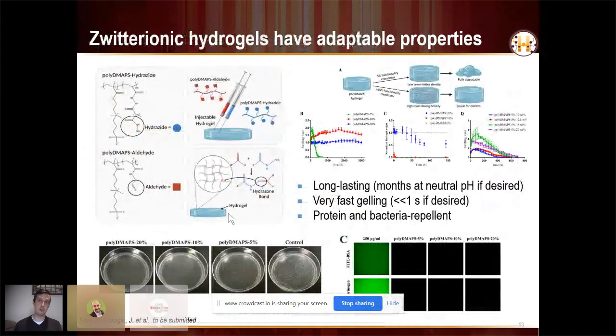Similarly, in the context of zwitterionic hydrogels, and this is using a sulfobetaine monomer, so it's the sulfonate, which has a negative charge, the quaternary ammonium that gives a positive charge. Functionalized in the same way with hydrazide and aldehyde groups and mixed with a double barrel syringe. What we end up with is, again, a variety of tunable properties.